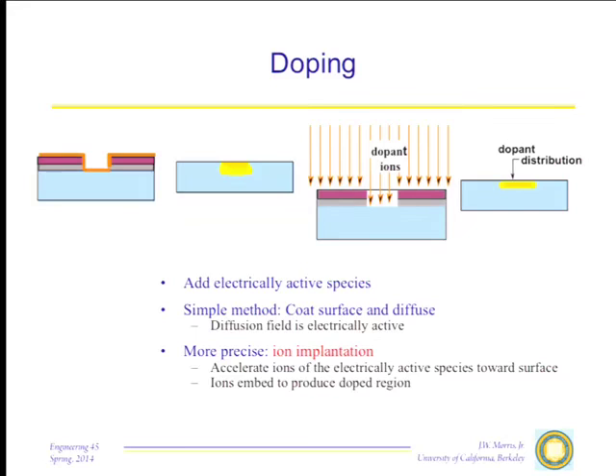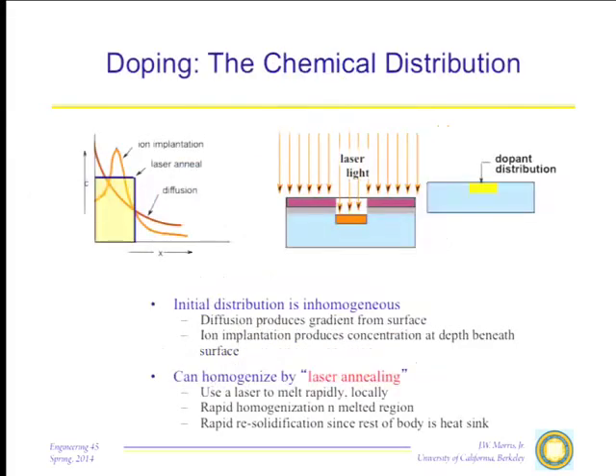There are a number of ways to do that more precisely. The more precise ways usually involve something like ion implantation, where we take our coated surface, we subject it to bombardment with dopant ions, and we get a dopant distribution something like this. The problem with diffusion as a way of generating your doped regions is that, I think I illustrate this on the next profile, yeah. If I just use diffusion, I get a diffusion profile that looks something like this. The dopant concentration just tails off as you go down into the material, and as you can see, that has the consequence that the conductivity of your semiconductor is going to be a function of distance below the surface. People can cope with that, they've done it for decades, but it is something of a problem.